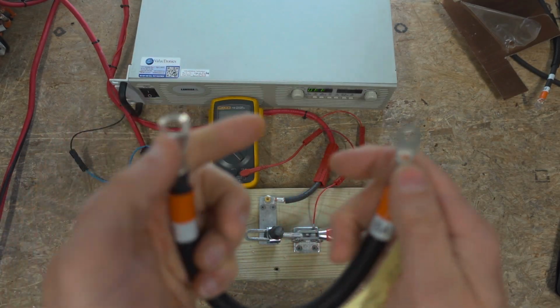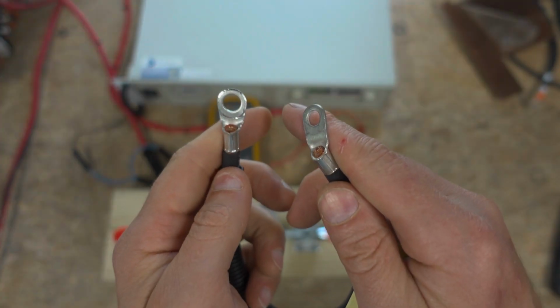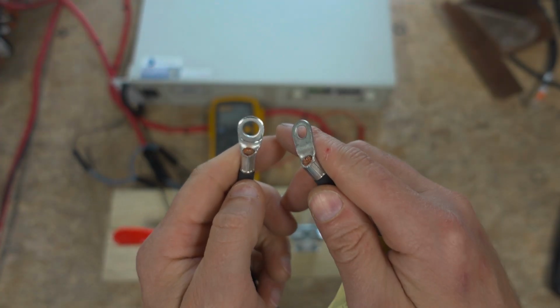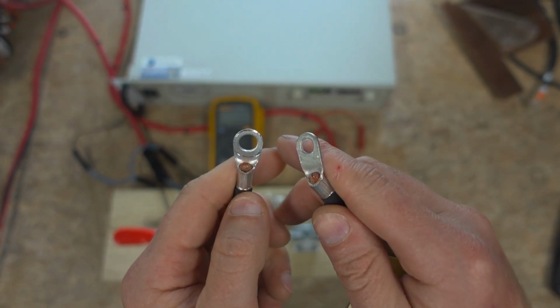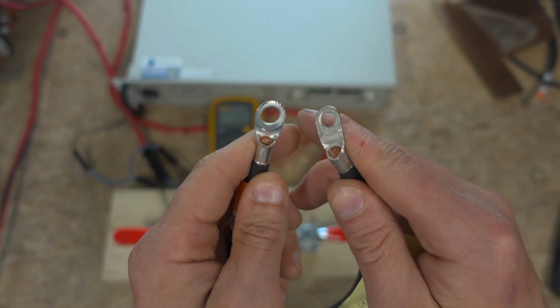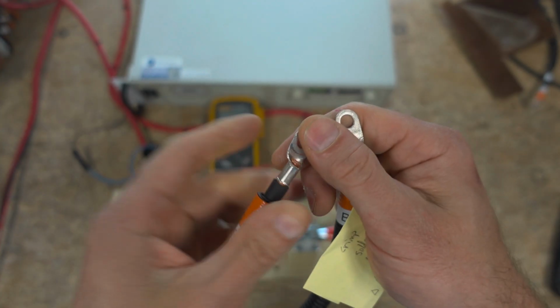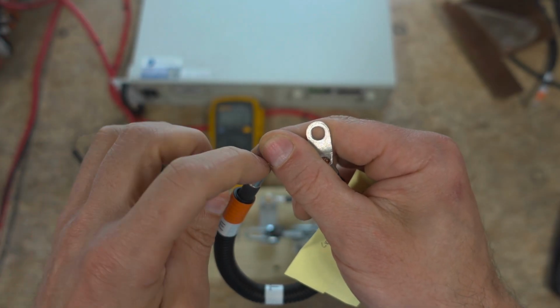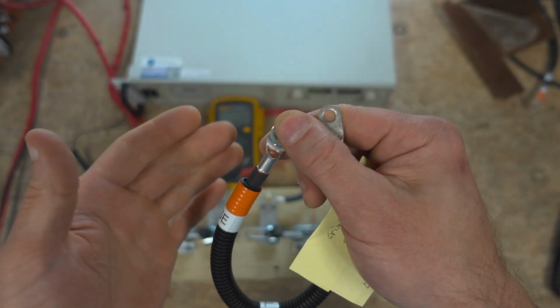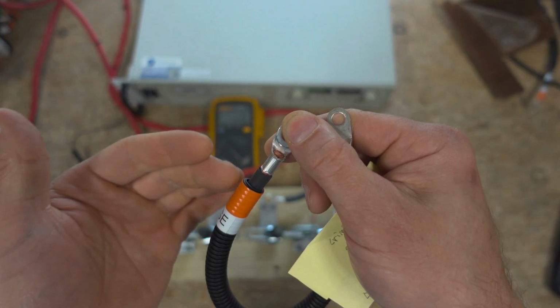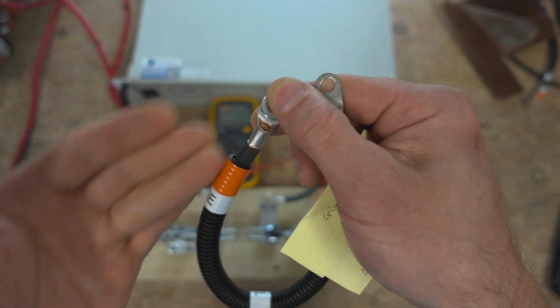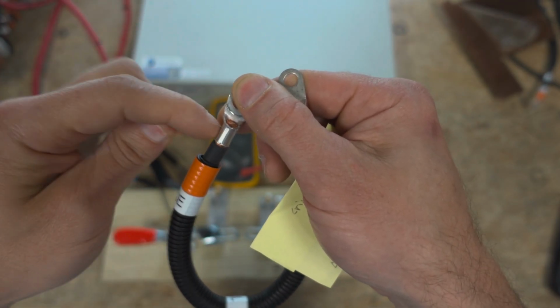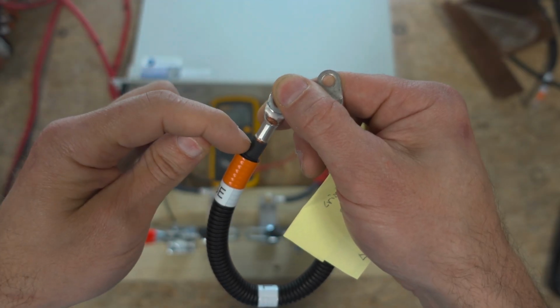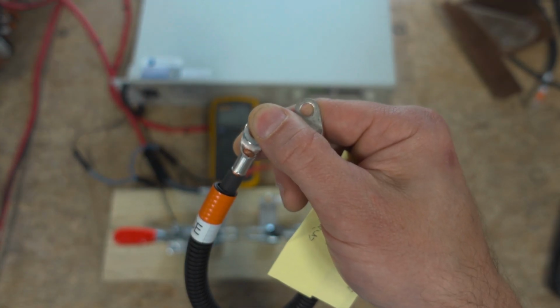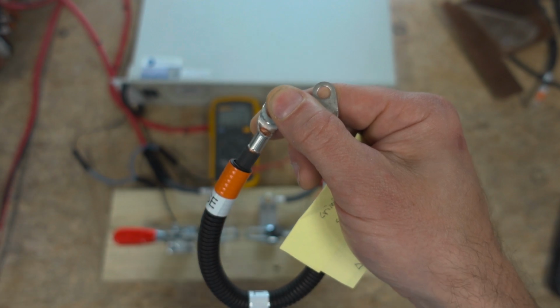There's a secondary argument made in this video talking about how environmental moisture will cause crimped contacts to fail. And that's just not correct if you have crimped it properly, because you get a cold weld. There's no oxygen in here to oxidize. So the outer copper can oxidize, and of course, in both cases, whether or not you crimp or solder it, you could have oxidation that causes your cable to fail, but it's not going to be in here at this joint, at least not any worse than soldering. So I don't buy that as a valid thing.